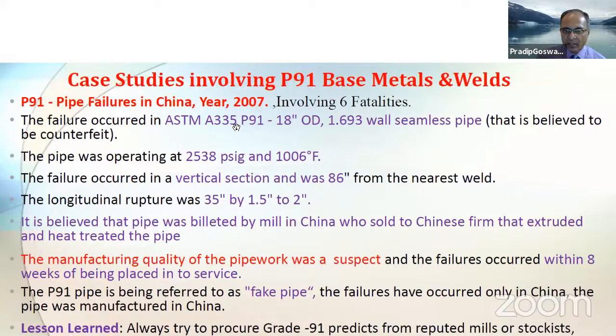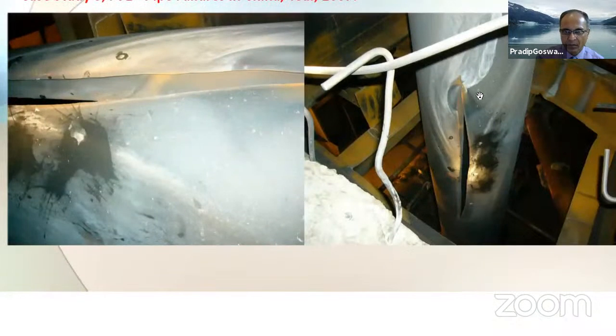This failure occurred in a P91 seamless pipe, approximately 1.6 or 1.7 inch, that is over 40 millimeter thick walled. This pipe was not considered to be genuine. It was later thought to be a counterfeit. The pipe was operating at something like 1006 degrees Fahrenheit, which is close to 540 degrees centigrade. The failure occurred in the vertical section and was away from the weld, almost 86 inches away from the nearest weld. These are the typical rupture sizes, 35 inch by 1.5 to 2 inch. I'm talking about this length. This was the typical length of the rupture.